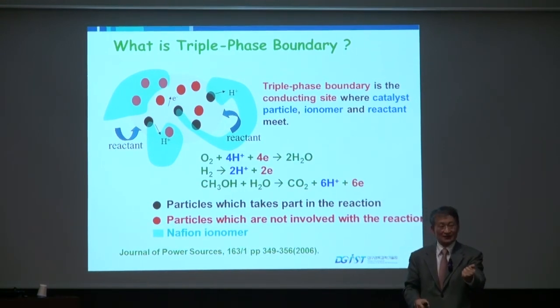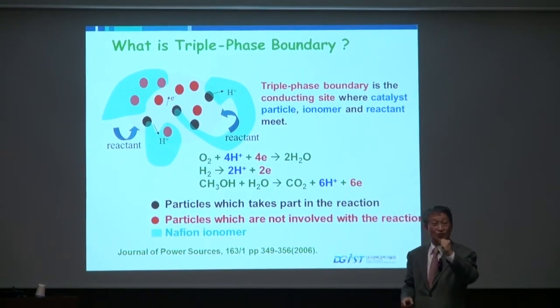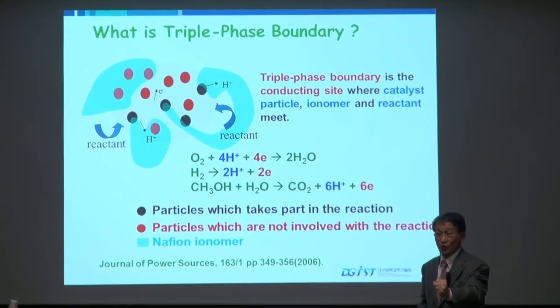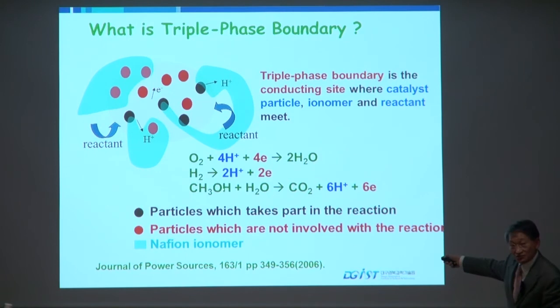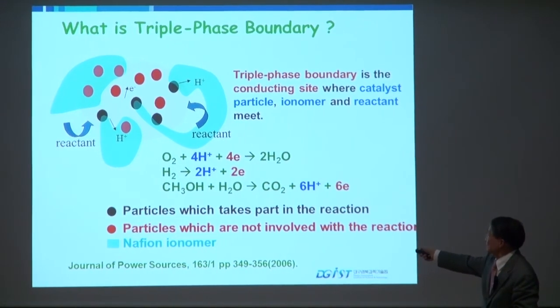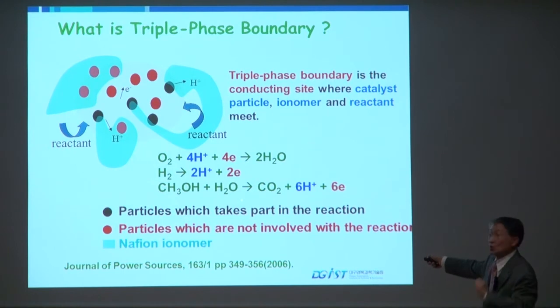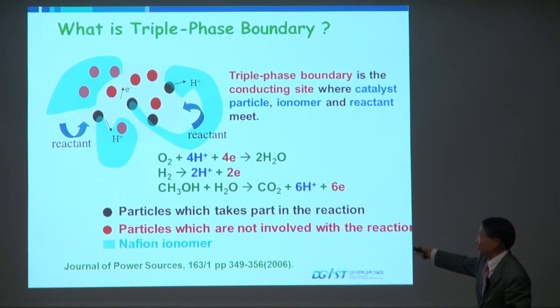So you have to have a catalyst, and you also have proton conductivity as well as electronic conductivity, because fuel cell reactions, oxygen reduction reactions, hydrogen oxidation, methanol oxidations, all involve the same number of electrons and protons. That means in order for these reactions to continue, you have to have suitable electronic conducting material for removing or supplying electrons. And also, at the same time, proton conductivity. It removes the proton or supplies protons.